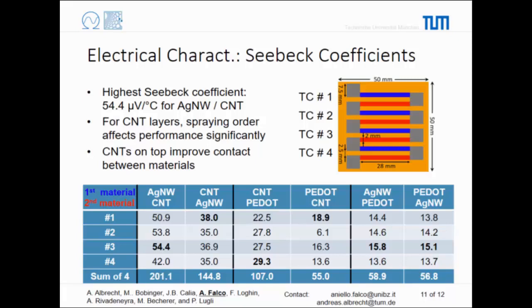The best combination we were able to achieve was with silver nanowires and CNTs. In the combination, first silver nanowires and then CNTs. It's not entirely clear why. We've been really thinking about it, reading into literature. We reiterated the experiment several times. That's the advantage of having master students helping you out. And we were consistently having the same results.